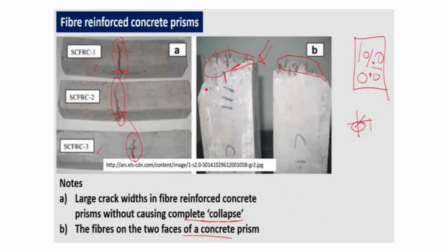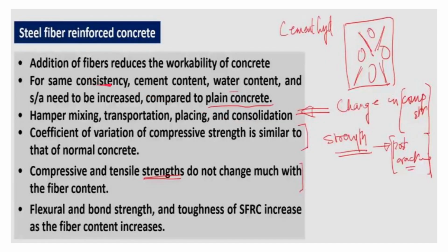As you can see in this case A, both are fiber reinforced concrete examples. In case A, you can see large crack widths in fiber reinforced concrete prisms without causing complete collapse. So cracks have appeared, but the beams have not collapsed. And in the second case B, the fibers on the two faces of a concrete prism, as you can see here, the fibers are popping up, right? So in steel fiber reinforced concrete, addition of fibers reduces the workability of concrete. So that is one of its drawbacks.